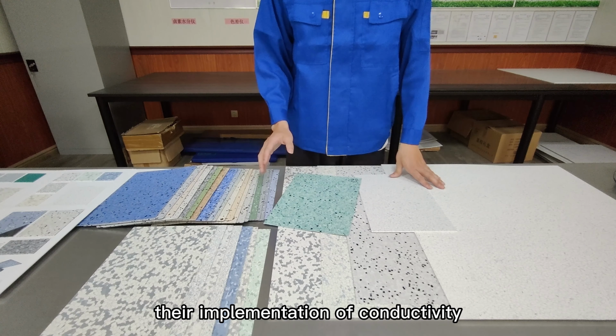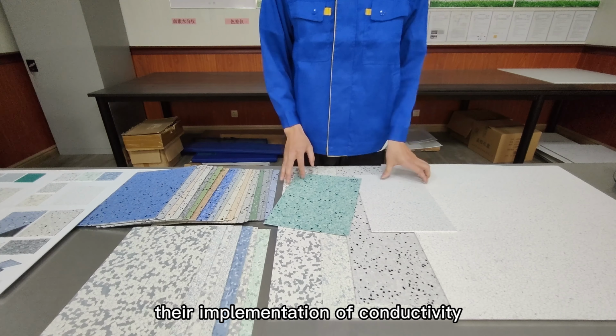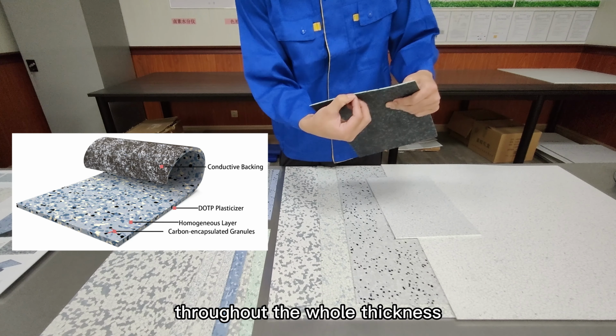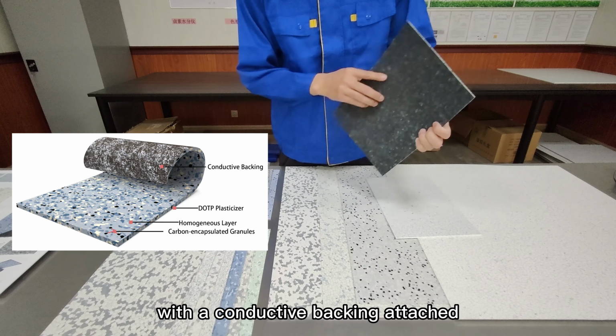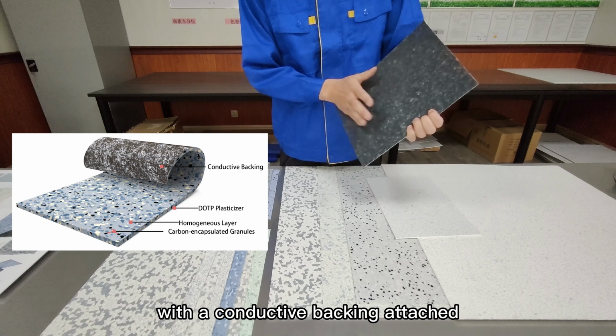Production also decides the implementation of conductivity. Tile utilizes the conductive network formed by the interface of plastic particles, and the sheet inserts conductive carbon granules throughout the whole thickness with the conductive backing attached. Both tile and sheet are homogeneous structure, but the sheet has better wear resistance. Tile wear resistance is P grade, and the sheet can reach a higher grade as T.